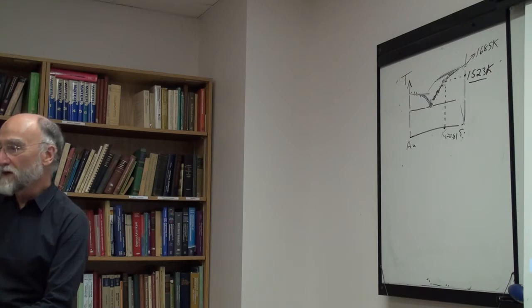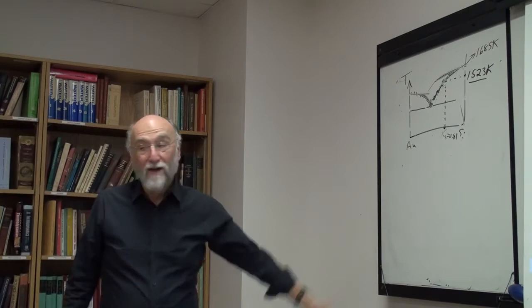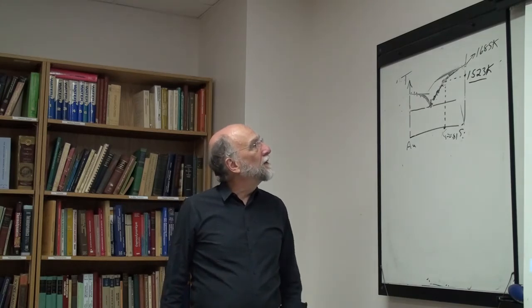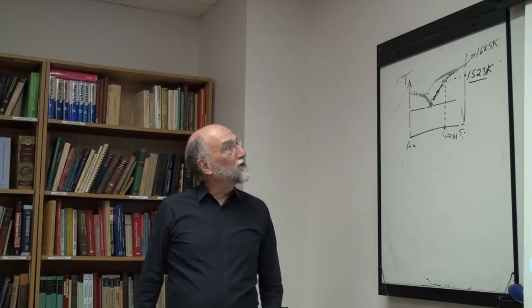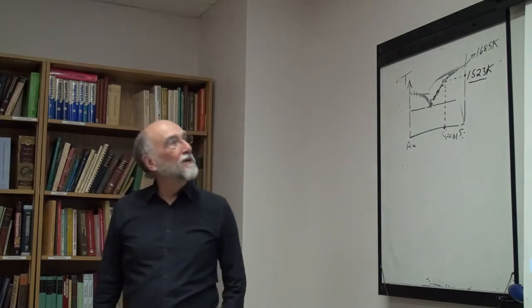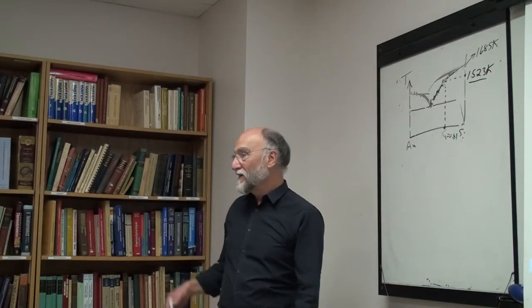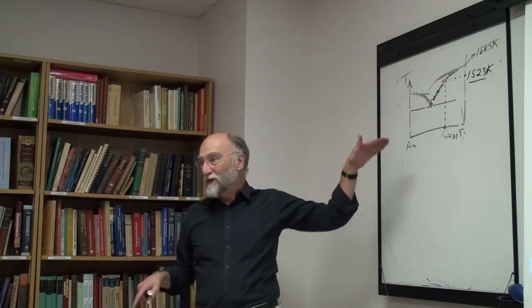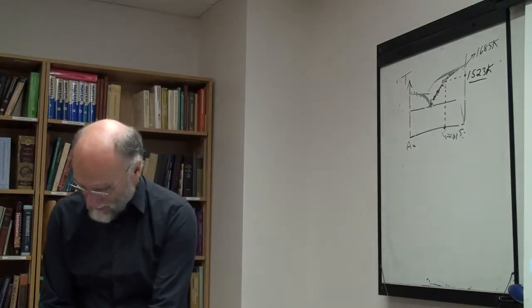Way back when I was a master's student doing some experimental work, I did some thermal analysis and measured a binary phase diagram. I used the heat of fusion that I got from the literature, and I found my limiting slope agreed quite nicely. But then I went back to the literature, and the heat of fusion in the literature had actually been determined by measuring the phase diagram and taking the limiting slope, so naturally it worked perfectly.